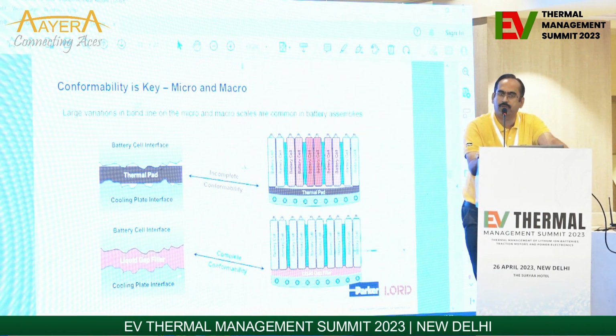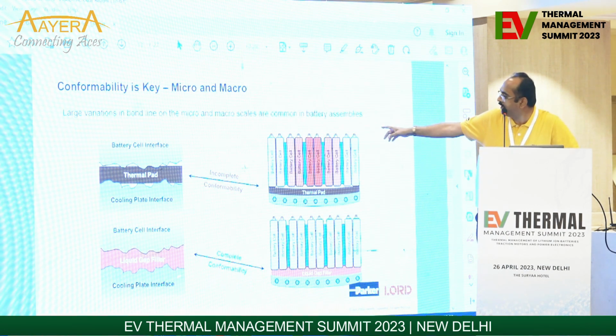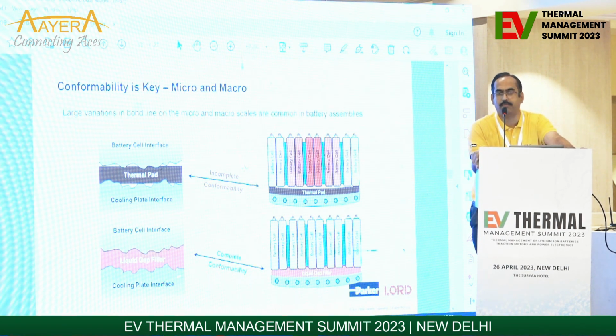This is basically about our gap fillers, and how they are better than thermal pads. If you look at a long cooling plate at a macroscopic level, there will be some imperfections. So pads will not cover all the gaps all the time. You can see gaps over there, which could be the probable hotspots. Here, our gap filler being a paste kind of material can go into all kinds of gaps, giving you better results compared to thermal gap pads. So it can cover all gaps and give almost 20 to 30% better results than thermal pads.